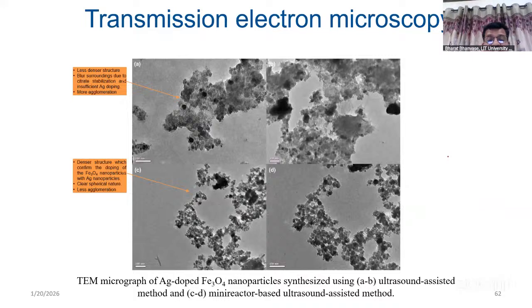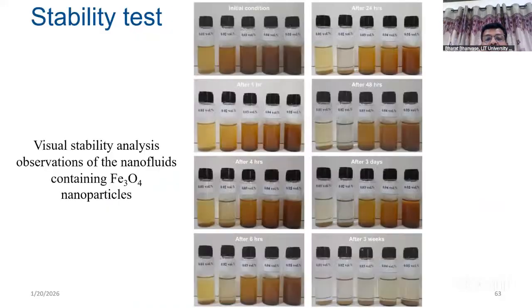But if you see the Ag-dope Fe3O4, so this is another one. You can see Ag doping is there on these particles, and then we have carried out the stability test. So this is initial condition at different volume percent. After 1 hour, you will observe settling, right?